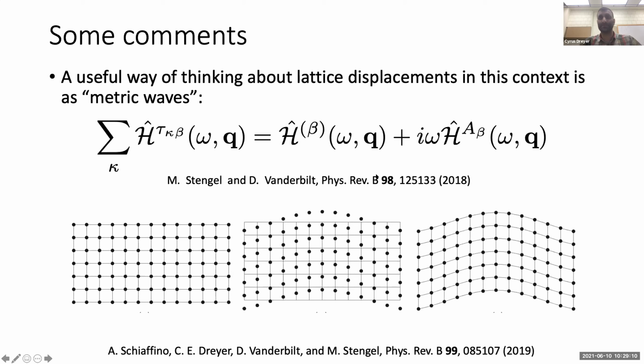And if we consider doing a metric perturbation, we can write again this sublattice sum of the atomic displacements, the perturbed Hamiltonian from atomic displacements, in terms of this metric perturbation. And then if we're at finite frequency, an extra vector potential perturbation. By definition, this metric perturbation vanishes at Q equals zero. And that gives us, again, a relationship between atomic deformation perturbations and vector potential perturbations. And that can also be another way of thinking of the relationship between the Born effective charge and the optical conductivity.